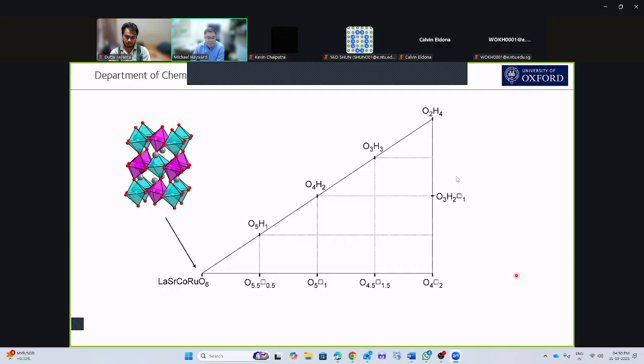phase diagram. And so what we have here is a slightly unconventional phase diagram of the anion lattice of this LaSrCoRuO6 system. So in the bottom left-hand corner, we've got our starting material. And then as I move horizontally along the bottom of this phase diagram, what I'm doing is I'm taking oxide ions out and adding vacancies. And what this does is it decreases the transition metal oxidation state. We're doing a reduction in this direction.